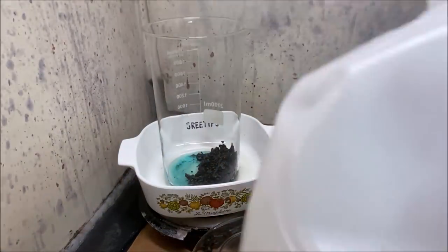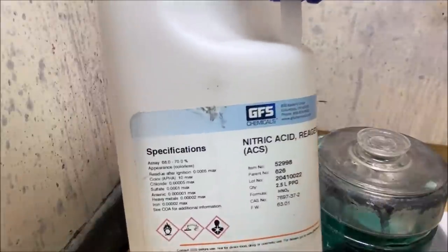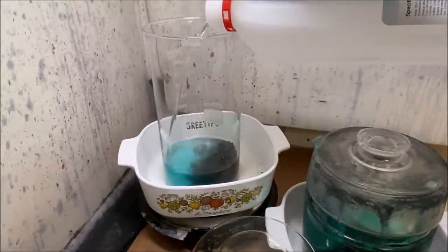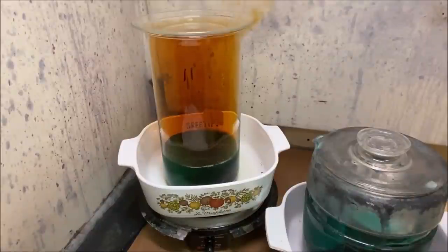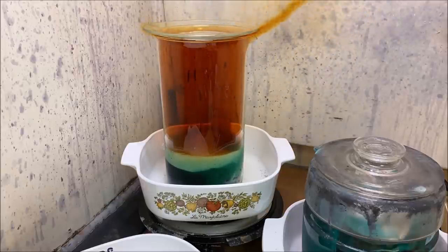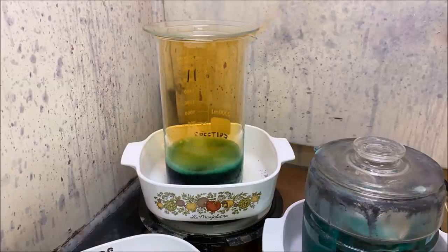I'm going to add some distilled water — a couple hundred milliliters or so — then add an equal amount of nitric acid, 68 to 70 percent nitric, and pour it right in. This should get a pretty vigorous reaction again. This is nitric acid treatment number two. This is about a 30-minute time lapse. As the reaction proceeds, fume production will start to decrease, which will let us know when all the nitric acid has reacted with the silver and base metals in that inquarted gold.